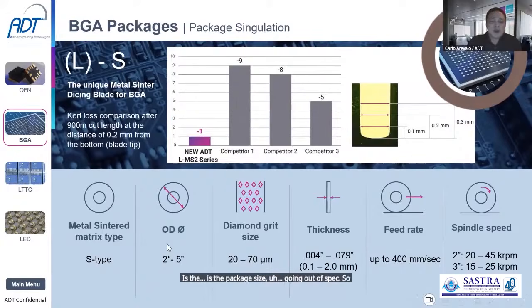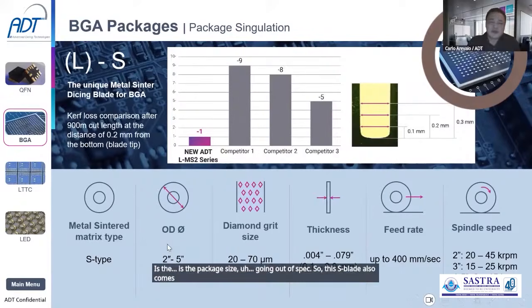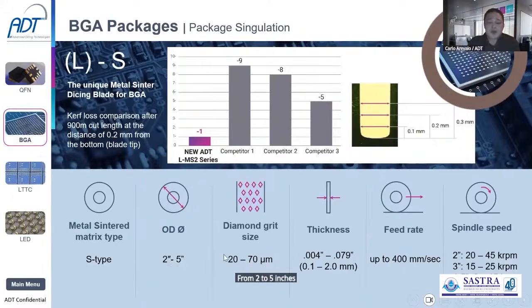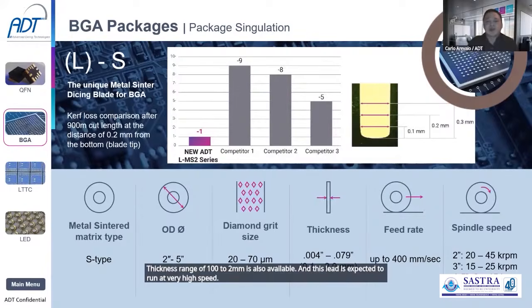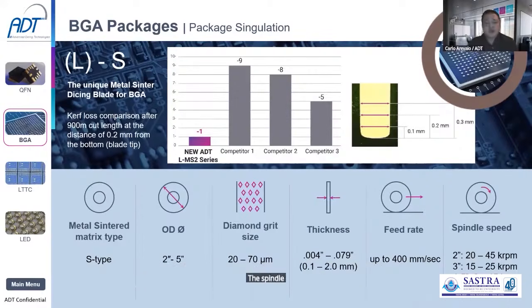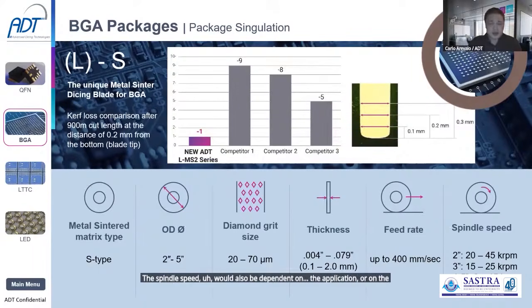So this S blade also comes in different OD sizes, from 2 to 5 inches. The diamond range is from 20 to 70 micron. Thickness range of 100 microns to 2 mm is also available. And this blade is expected to run at very high speed, at 400 millimeter per second. The spindle speed will also be dependent on the application, the equipment being used, or the blade OD.